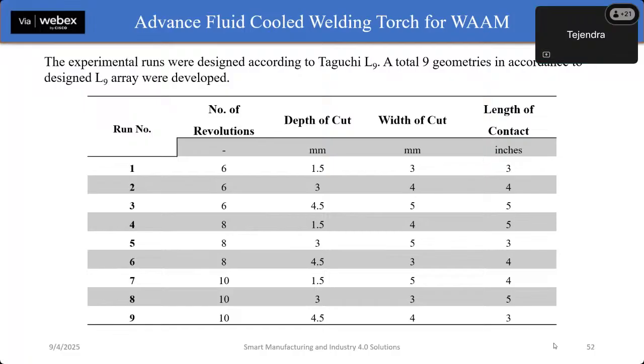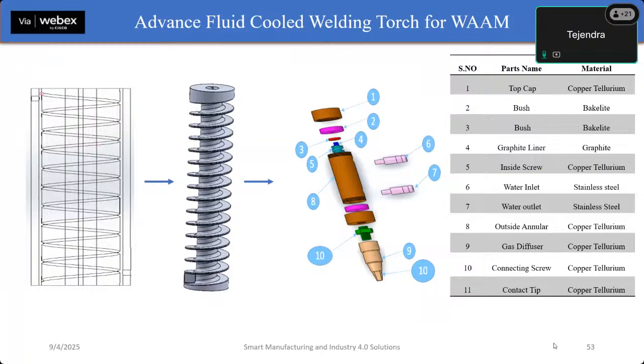The experimental run was designed, and as per the experimental run, we developed different types of nozzle for the torch. This is the solid model of the torch along with the bill of material. The top cap, the inside screw, the outside annular, the gas diffuser, the connecting screw, and the contact tip were fabricated using copper tellurium, while bakelite was used for the bushes and stainless steel was used for the water inlet and outlet.